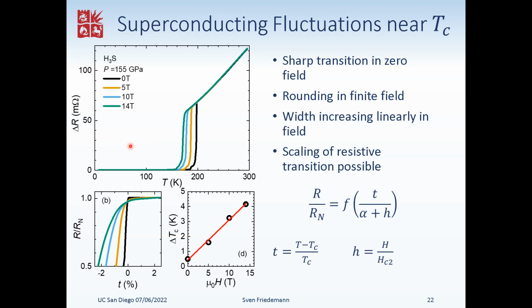Whereas in hydrogen sulfide, we have a metal, and hence we've got some bonds. In fact, important bonds for the superconductivity, antibonding states of the hydrogen sulfur bonds. We've got them right at the chemical potential, so they will immediately respond to a pressure release, and hence I don't see a way to have this metastable state recovered to ambient pressure.